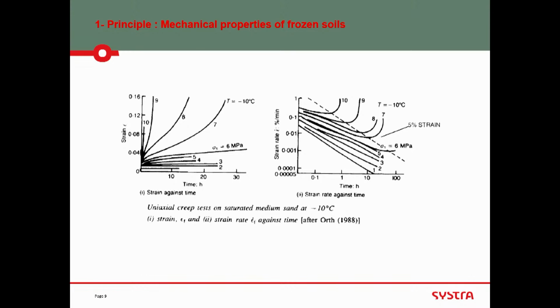What you see is that there is a divergence, so an increase in strain velocity, epsilon dot, at this point. So it means that the slope is changing. This slope changing, in fact, tends to be for the same strain level. Which means that here you go very quickly to failure. Here you'll go less quickly to failure, but you'll start diverging. The phenomenon has been engaged for the same strain.